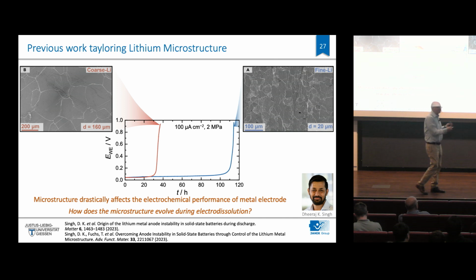So we could use different foils, but the problem is then you really have to produce them. And the question is, is that really stable? And of course, nobody really wants to bring lithium foils into a battery. The ideal concept is to have all the lithium in the cathode, and in the first charge step, just produce the lithium, but not bring lithium as a foil into the cell. It is expected that it is pretty expensive to have thin lithium foils. So I think the best is to have an anode-free cell concept where all the lithium from the cathode is used in the first step to make a metal.